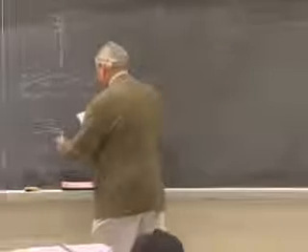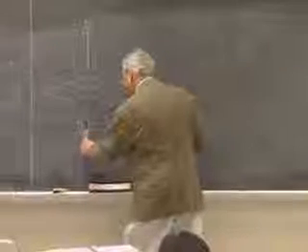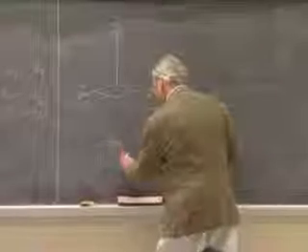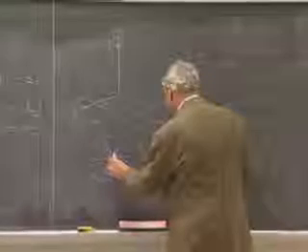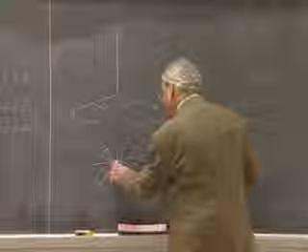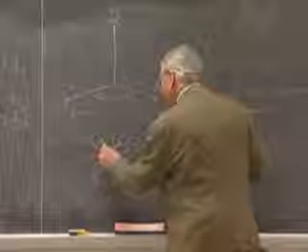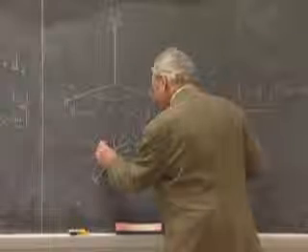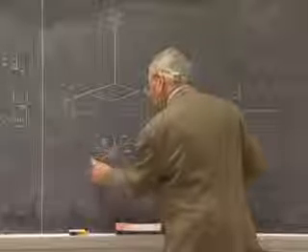So the way this is going to go from x1 is going to be a positive lobe around x1. There's going to be a negative lobe along x2, and then a positive lobe again about the twofold axis that's 120 degrees away. And then a negative lobe, and then a positive lobe opposite this negative lobe, and a negative lobe opposite this positive lobe.